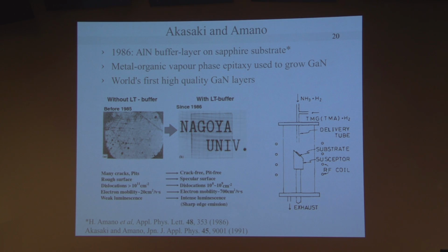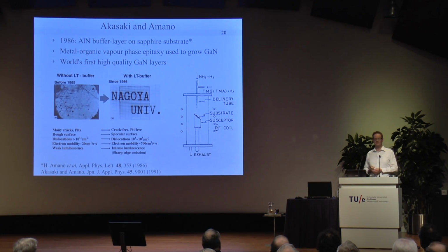This is the setup that they used. They used metal organic vapor phase epitaxy to grow this crystal. The way it works is you have a chamber and a substrate. You heat the substrate, and you add precursors of the gallium and the nitride component, and they react on the substrate, and then you get a gallium nitride layer. And it's interesting to note that all these papers are in APL and Japanese Journal of Applied Physics and Journal of Applied Physics, and maybe that's a consolation to some, that if your paper does not get accepted in Science and Nature, you might still have a chance at some point, perhaps, who knows.